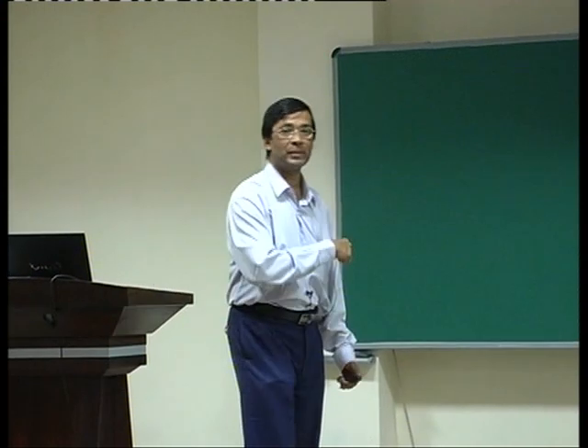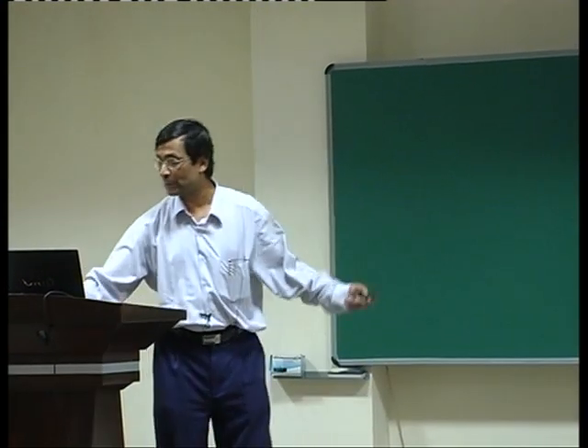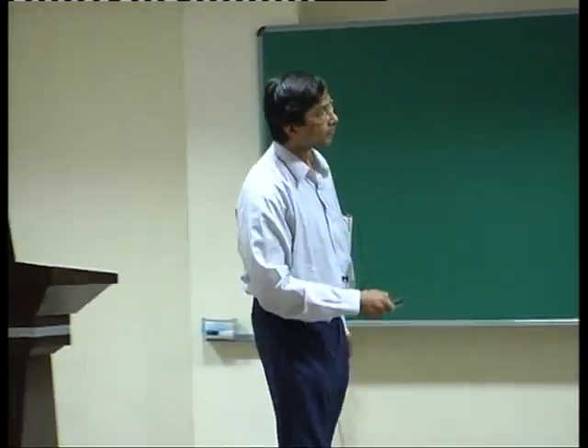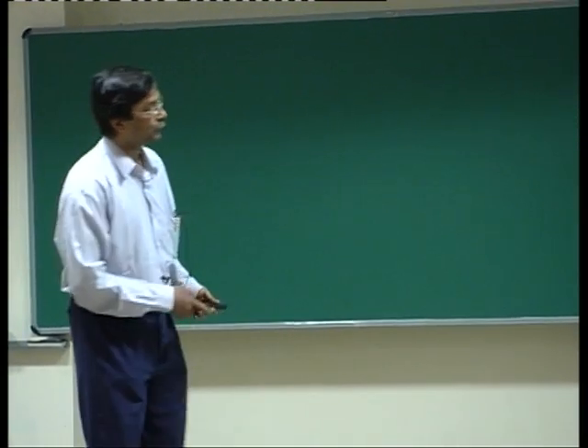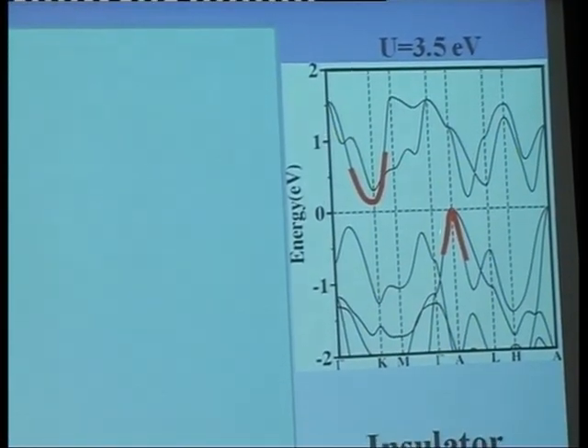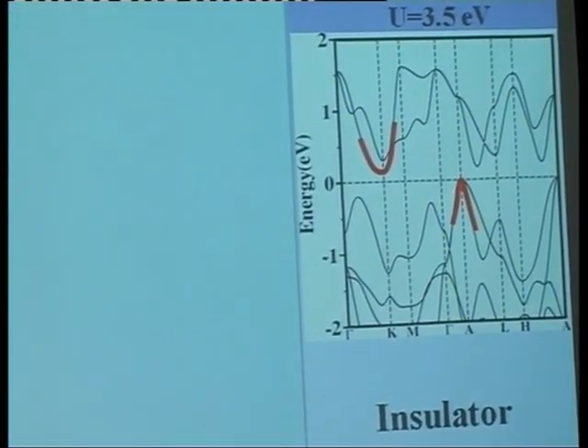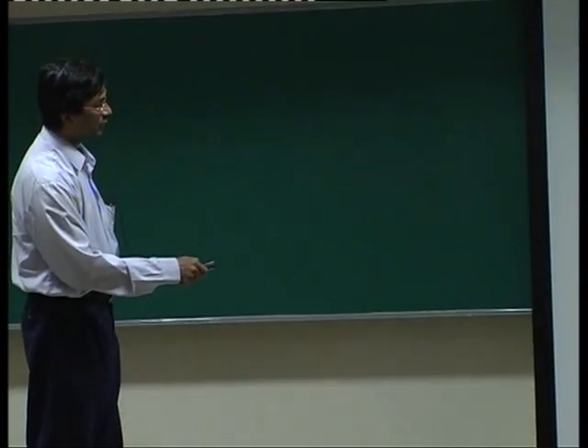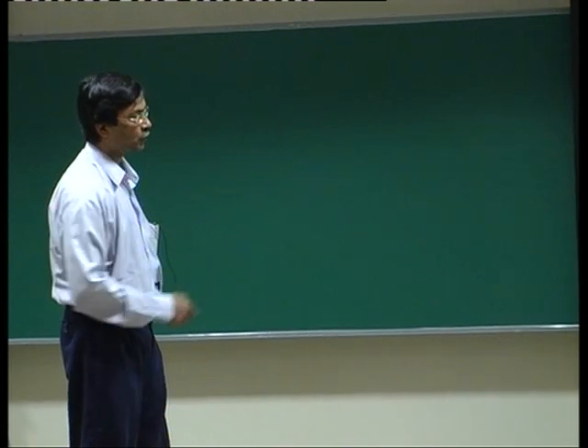But first, to tell you that this schematic is exactly what we are looking at, I'm showing you the insulating state again at 3.5 electron volts. If you look at this insulator, you can see the gap, and these are the two pieces that you're interested in. There's actually a degeneracy, I'm simplifying it. You can think of the two parabolic things out there and one here. And as I decrease U, the schematic will come closer and closer, and this piece and that piece transfer electrons, creating holes and electron pockets. Right? And that's what gives rise to this Fermi surface, which is completely different from the other one.